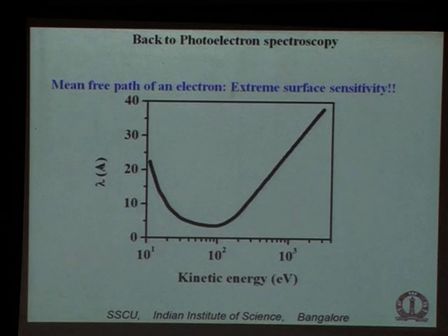So the penetration depth will also be proportional to the wavelength of the incident? This is exactly the dependence, because the kinetic energy varies linearly with the photon energy. So instead of kinetic energy, I can define photon energy minus the binding energy. So given a fixed binding energy, it's a photon energy axis. And that tells you how it varies with photon energy. So then looking at the x-axis, it does seem that the losses through phonon modes are actually quite small, because the phonon energies are sub-electron volt. Yes, but I can excite many.